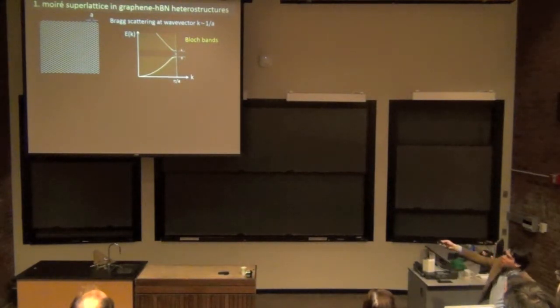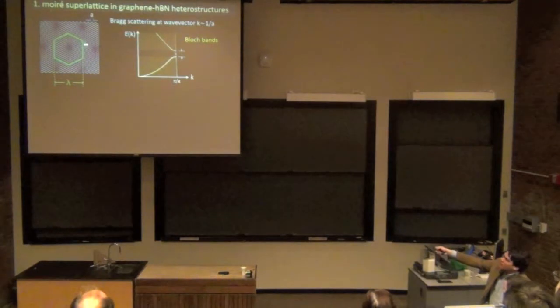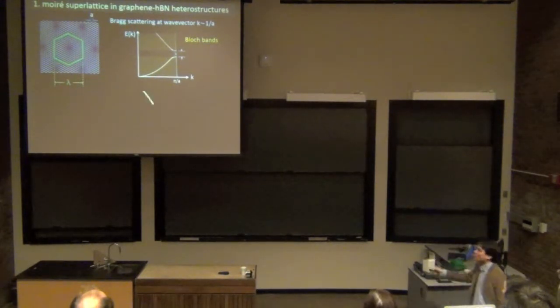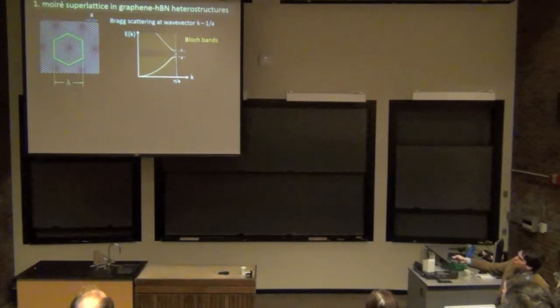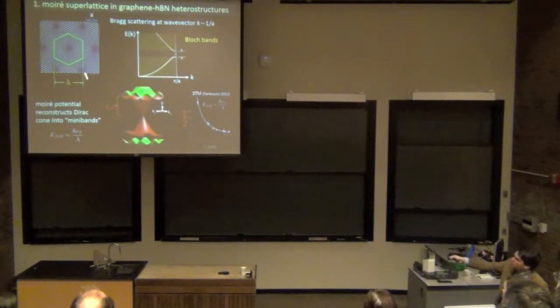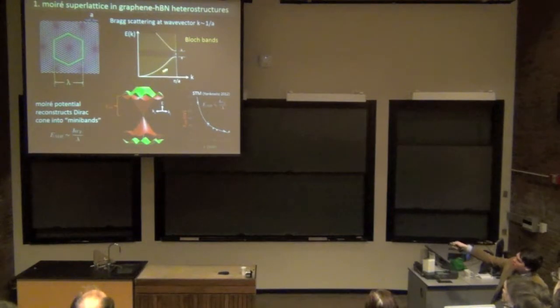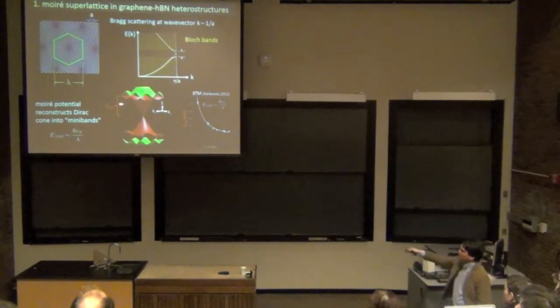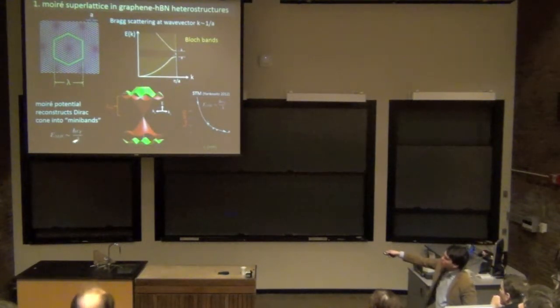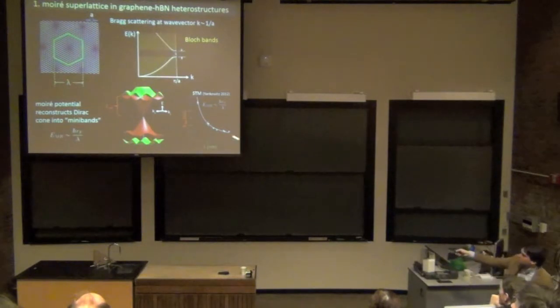So you might be able to imagine what happens when you actually have this moiré pattern. This thing acts like a periodic potential that doesn't have a period of a, but has a period of lambda, now roughly 10 nanometers. And so basically what happens is that this moiré potential reconstructs the normal Dirac cone into so-called mini-bands. So at finite energies away from this Dirac point, you see this reconstruction of the electronic structure. And this energy is proportional to one over the wavelength, as you would expect. And this is also seen from STM measurements from our collaborators.